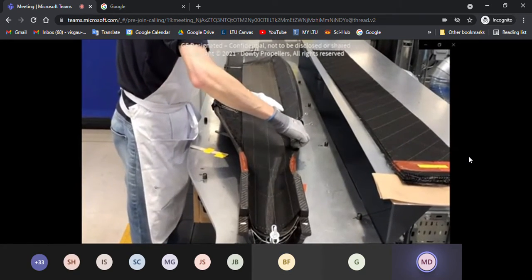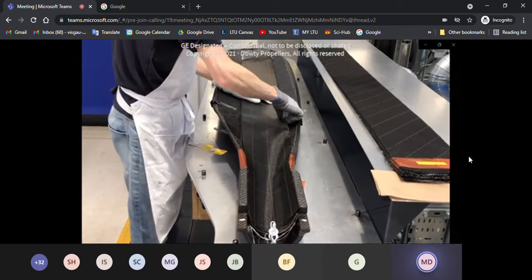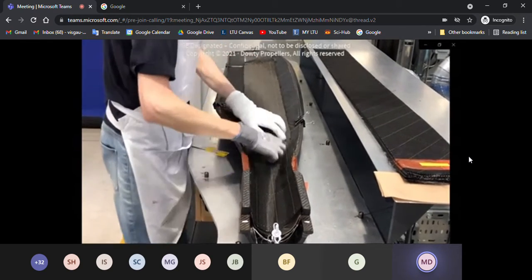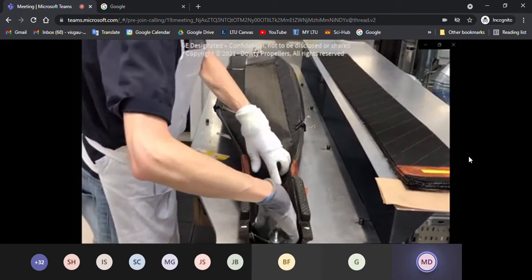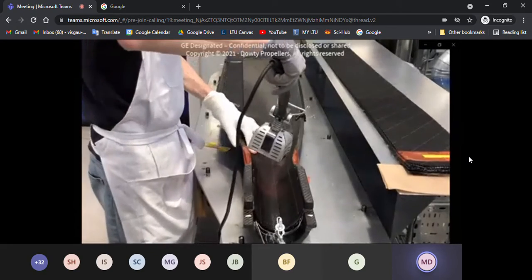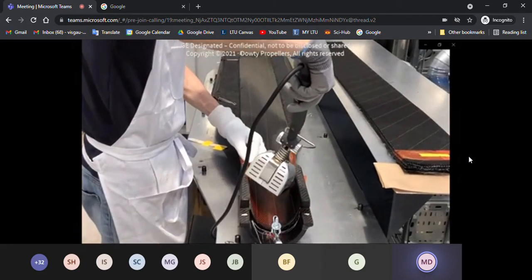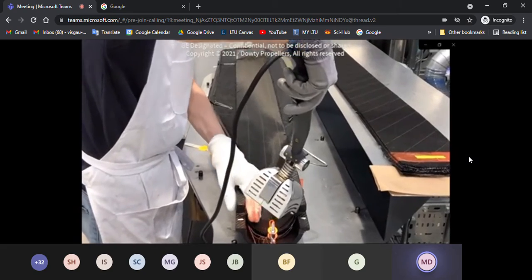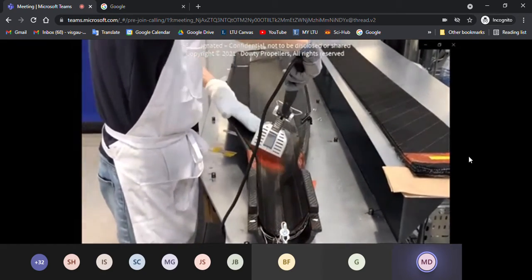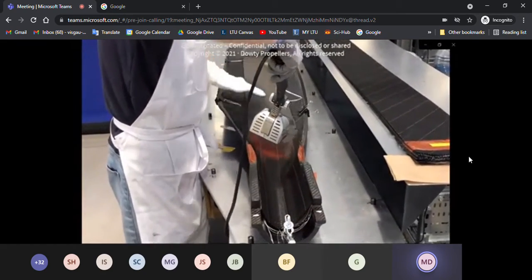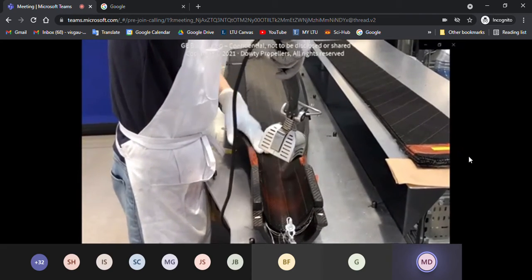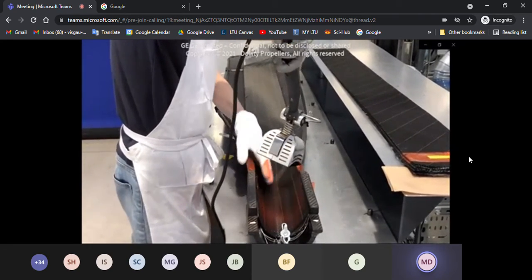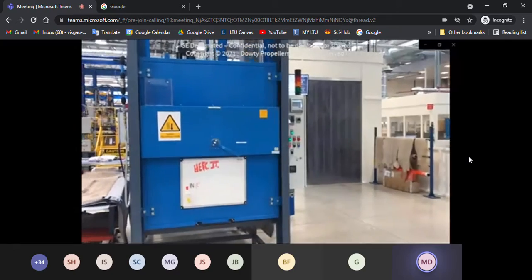the plies there. These plies are all dry, so they have no tack until the binder material is heat activated, which you can see the operator doing now. So he's using an infrared heat gun to activate the binder so that all the plies can be stacked together. Now this looks like quite a simple process, but it's actually very labor intensive and takes a lot of skill and a lot of time to learn.